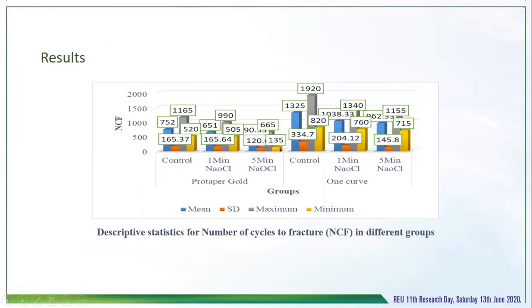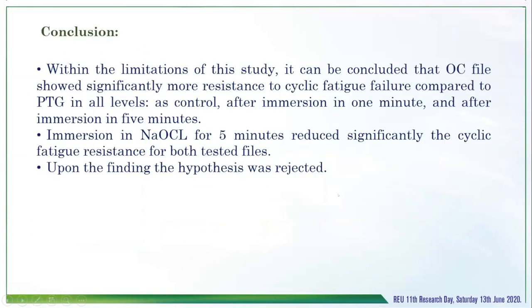Also, there's a significant difference between the control group and 5 minute immersion for both groups. So my conclusions: within the limitations of this study, it can be concluded that the One Curve file showed significantly more resistance to cyclic fatigue failure compared to the ProTaper Gold at all levels, as a control, after immersing for 1 minute, and after immersing for 5 minutes. Immersing in sodium hypochlorite for 5 minutes significantly reduced the cyclic fatigue resistance for both tested files. Upon this finding, the hypothesis was rejected.